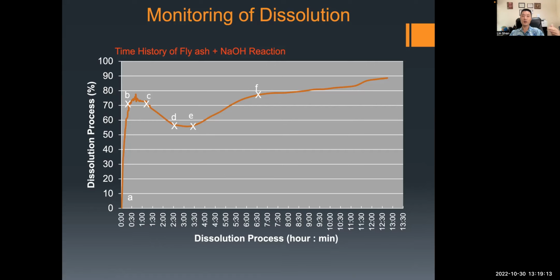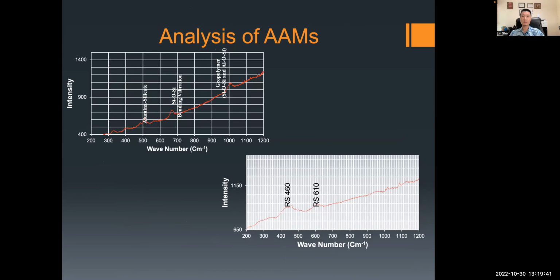So by doing this, we can get information such as suitability of precursors. It can also help us optimize the concentration and amount of activators. It can also help us optimize the mixing time and mixing procedure so we can reduce the cost and optimize the performance. We can also use Raman to detect the final hydration product. In this case, we have NASH, CASH, and also aluminum silicate bonds.